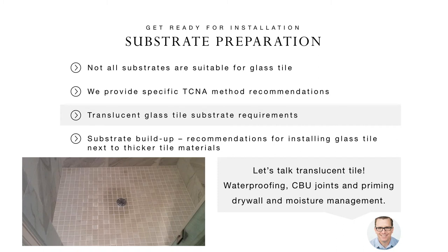For example, waterproofing with a translucent tile can be problematic. We do not recommend for shower applications that you have a topical waterproofing over your substrate with a translucent tile installed directly over it. The reason is moisture can get trapped between those two layers in the thin set and can cause some darkening. We talk about treating CBU joints, allowing them to cure for a full 48 hours.